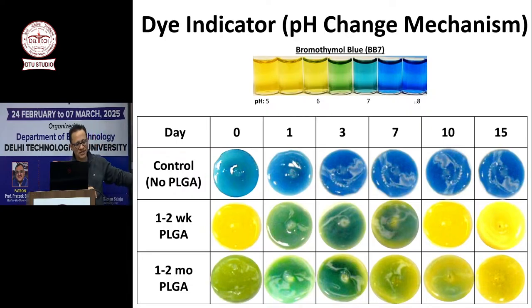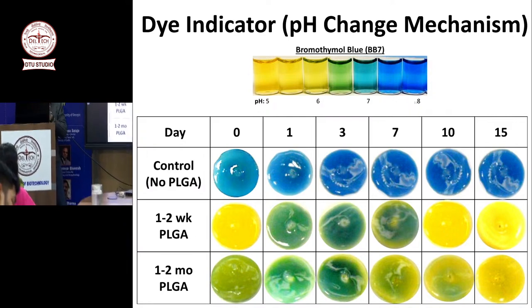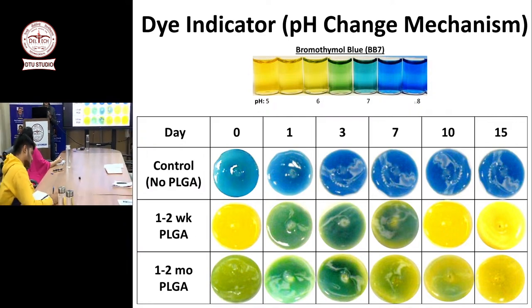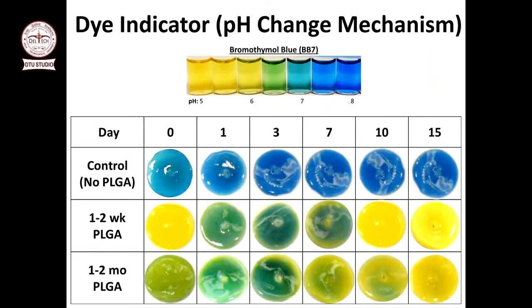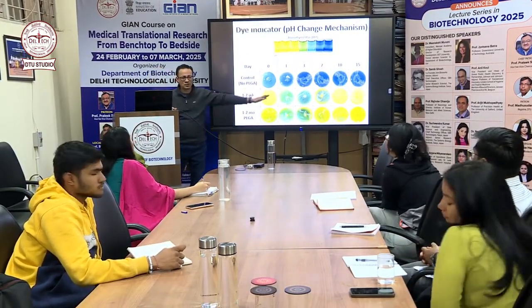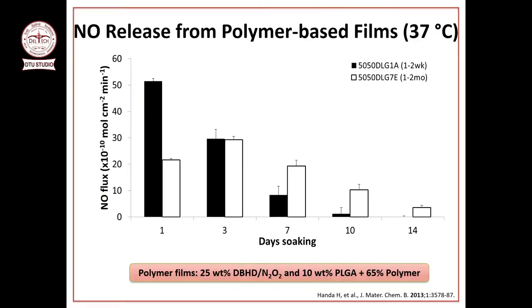When we had 1 to 2 week PLGA, your coating is yellow because your PLGA is breaking so fast that it's making a very acidic environment inside the coating. But it's releasing nitric oxide, making some diamine species, pushing it to a bluish color because it's fighting to make it a basic environment. That's why it's landing on green, because it's somewhere in between yellow and blue. But by day 7, all the nitric oxide is gone. And now PLGA won the battle. PLGA is making it acidic. There is no nitric oxide donor left to make it basic anymore. That's why it turned yellow, it's done. And that matches here also, that by day 7, day 10, your NO release is dead.